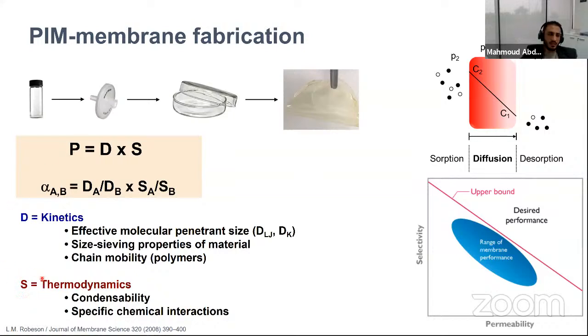The other factor is solubility. Solubility is a thermodynamic factor depending on the condensability of the gas and on specific chemical interactions that could happen between the gas and the polymer chains. Once we obtain the permeability of a specific gas, we plot it on this curve. This is known as a Robeson trade-off plot, where you plot your permeability and selectivity, and you see your performance compared to what has been reported in the literature or what exists as commercially available materials.